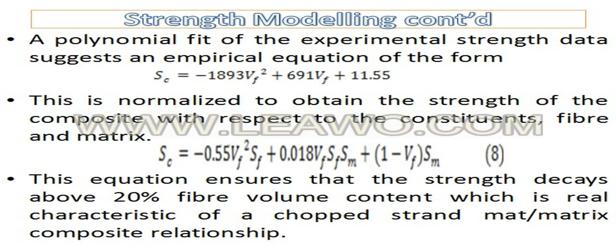If you look at the other models, they have a linear model with fiber volume fraction. This can be because for unidirectional, yes, but for fiber mat, the orientation of the fibers are not in one direction. And when you start pulling them, some are not actually contributing, especially with the increase in fiber volume fraction and less binding. And so you start losing strength with more fiber volume fraction.